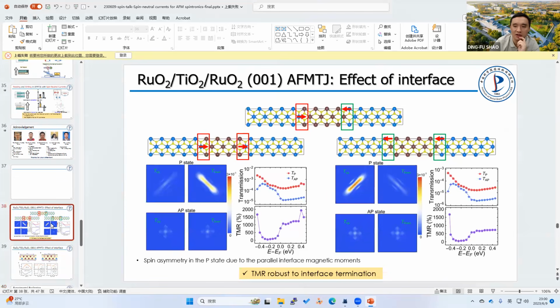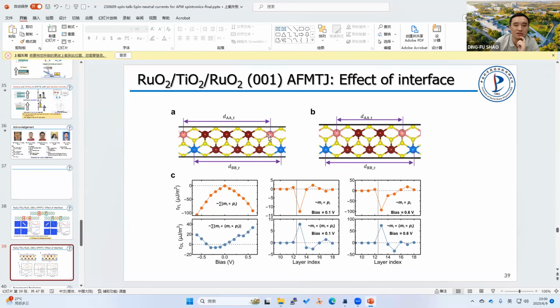Well, for TMR and STT, we have tested different terminations. We found that the TMR is always positive. And if we consider the roughness at the interface, we'll average these effects, because we always have these positive giant values, so by averaging, these effects will still be there. And for STT, we also consider different cycles of the barrier to get different interfacial terminations. And in this case, we found that we still have a sizable dominant field-like torque.